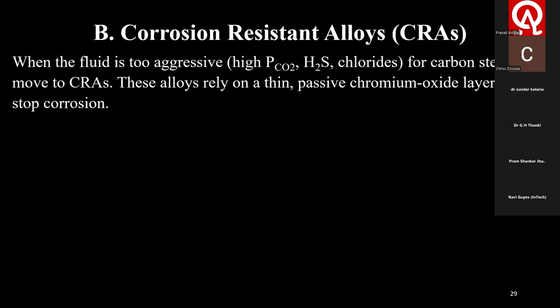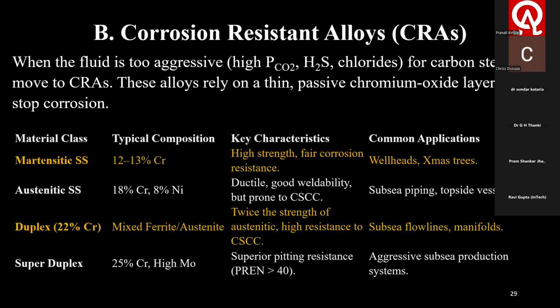Corrosion resistant alloy, CRA. When the fluid is too aggressive, high partial pressure of carbon dioxide and H2S, which is a problem for carbon steel, we move to CRA. These alloys rely on a thin passive chromium oxide layer to stop corrosion. This is just to give you a trivial form. Materials: stainless steel, austenitic stainless steel, duplex, and super duplex. But the typical composition I will try to show you.